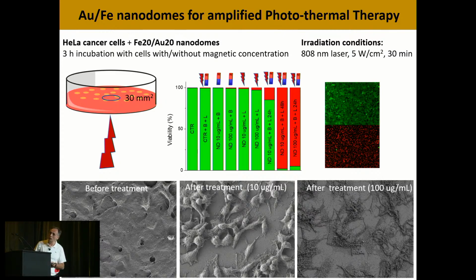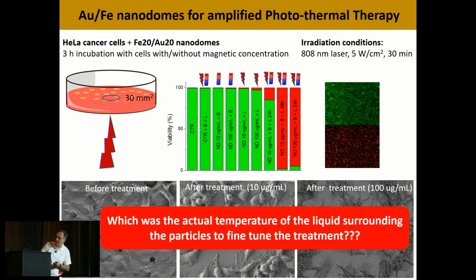But when we use 10 micrograms per milliliter, you see that the cells change morphology, but they still look like cells. This is because they are dying by apoptosis, which is a type of cell death that is much more controlled and has no side effects. So this difference made us ask the question: what's the actual temperature during the treatment? Why were these ones dying by necrosis, and why were these ones dying by apoptosis? So we designed a new experiment to see, can we really measure the temperature inside the cells?